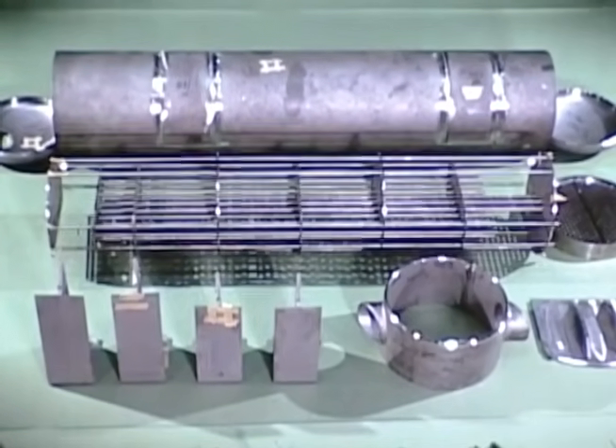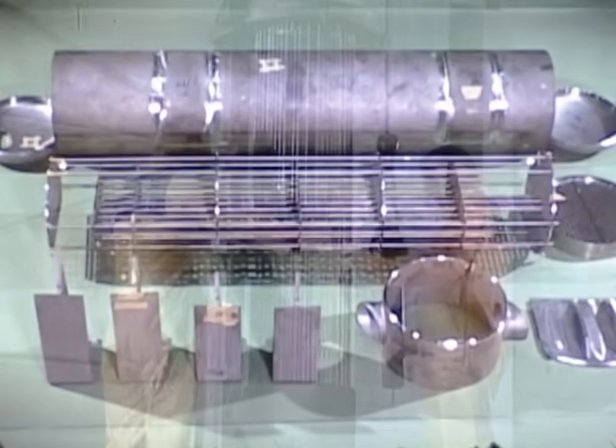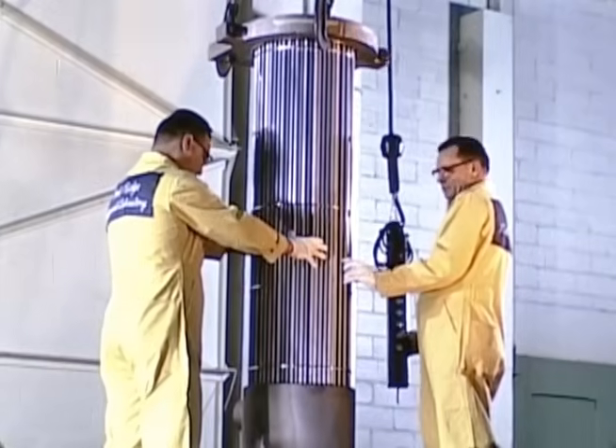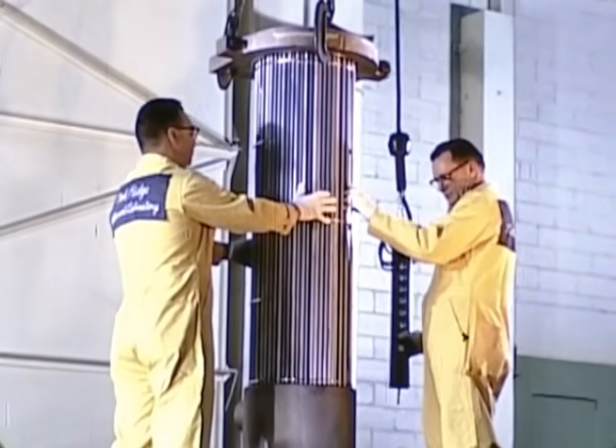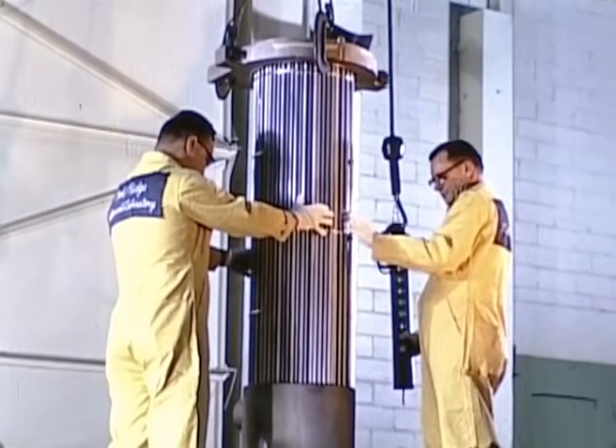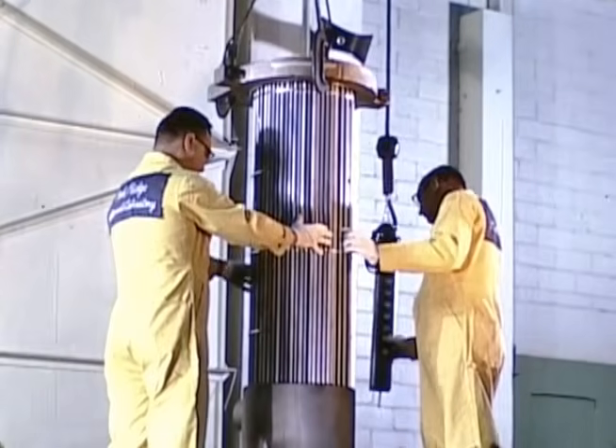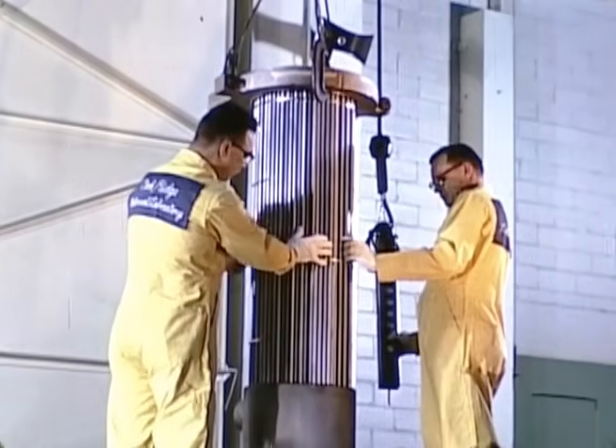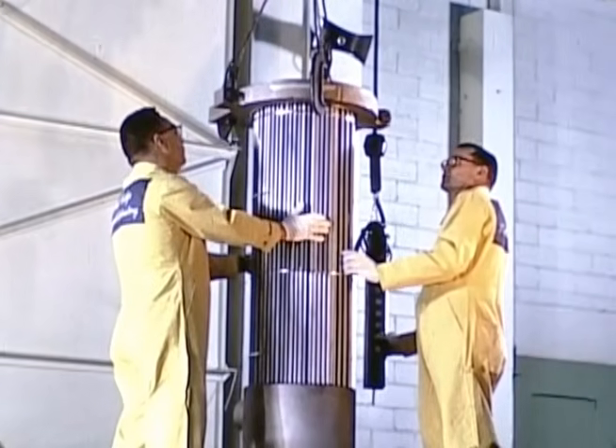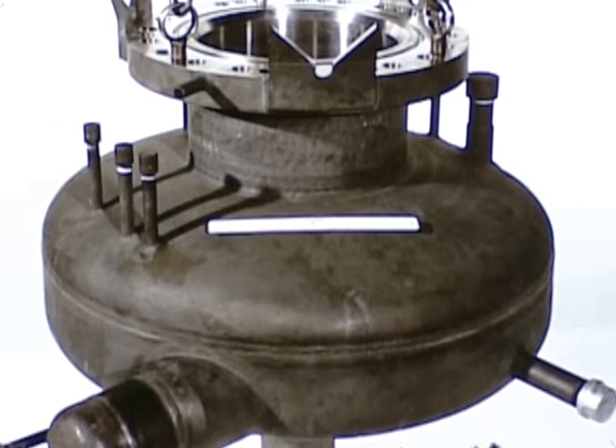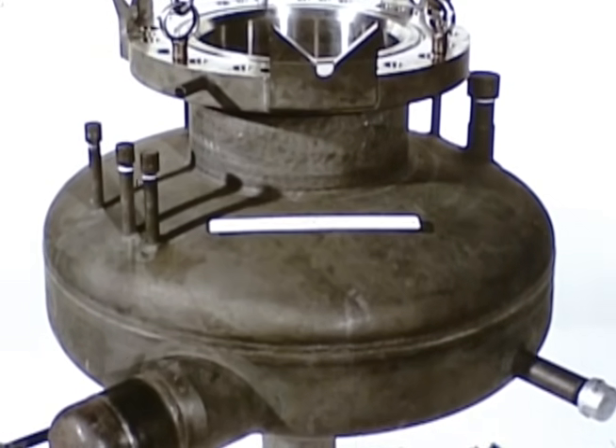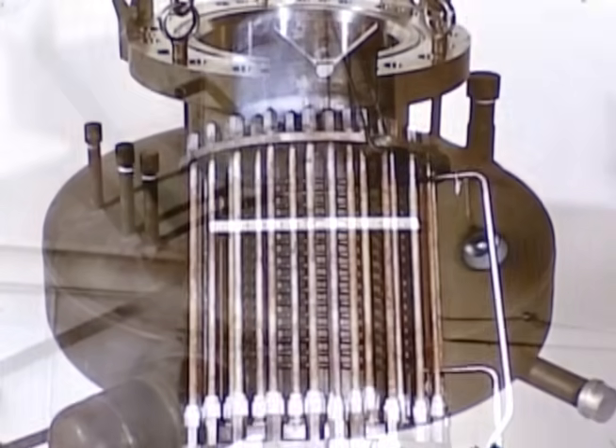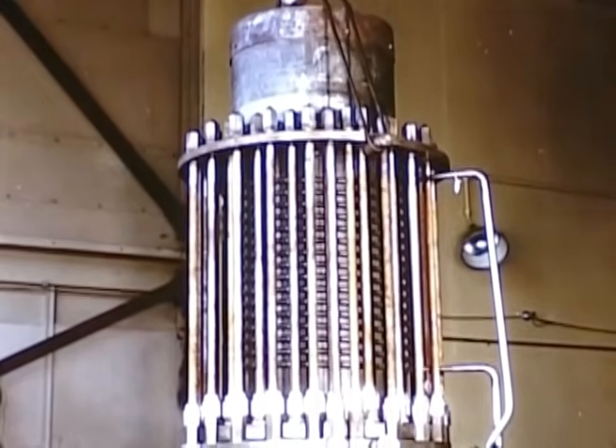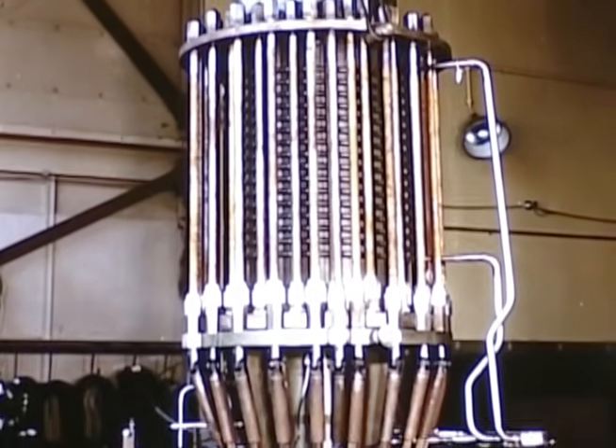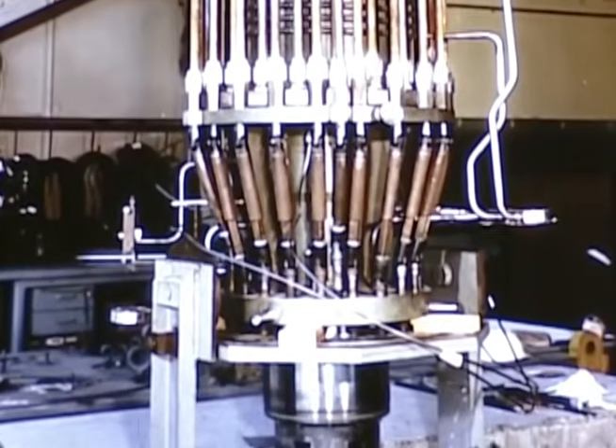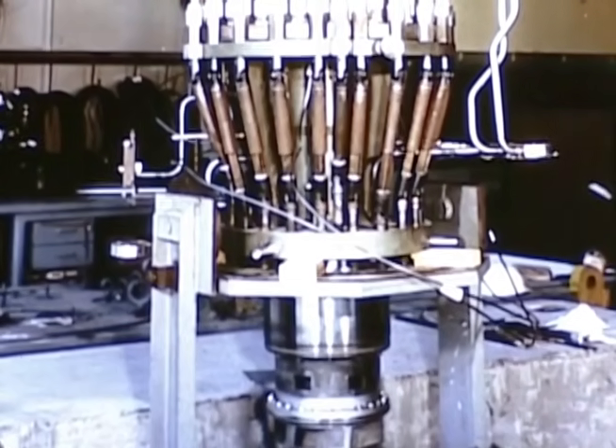The horizontal shell and tube primary heat exchanger is about 8 feet long. Its U-shaped tubes, 1/2 inch in diameter, were fusion welded and furnace back brazed in a hydrogen atmosphere to the tube sheet. The bundle contains spacer bars tightly laced in 2 directions through spaces between the triangular pitched tubes to eliminate flutter and vibration. The fuel salt pump bowl serves as the pump sump and normal volume to allow for expansion of the salt. This fuel pump rotary element with water-cooled drive motor, bearing assembly, bolt extensions for remote replacement, and impeller circulated molten salt at 1200 degrees during the non-nuclear run-in test.